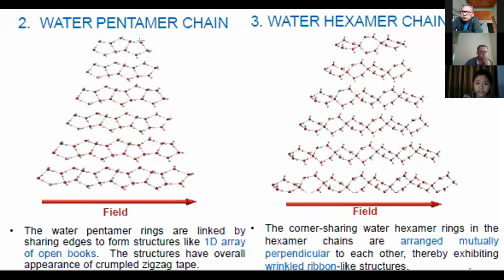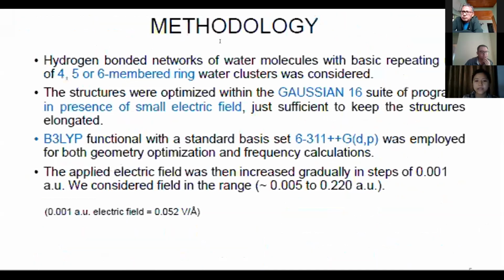Likewise, we have the water hexamer chain with the basic unit of a hexamer ring comprising 6 water molecules. Again, the shortest chain has 3 units of hexamer rings, and the largest has 8 units. So here we have 3 units, 4, 5, 6, 7, and 8 units of water rings. Next, considering these structures, we have optimized the system using the Gaussian suite of programs in the presence of an electric field. The level of theory chosen is B3LYP with the standard basis set 6-311++G(d,p). This level of theory is used both for geometry optimization as well as for frequency calculation. We applied the electric field and increased it gradually in steps of 0.001 AU, and the field range considered is 0.005 to 0.22 AU.